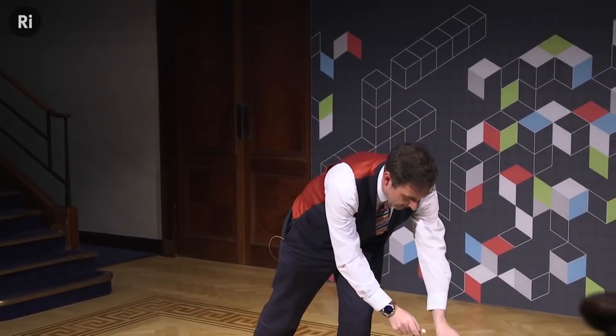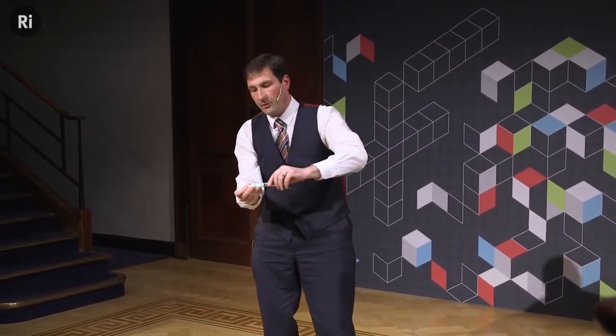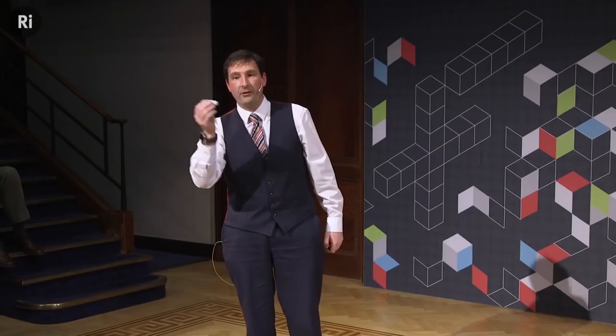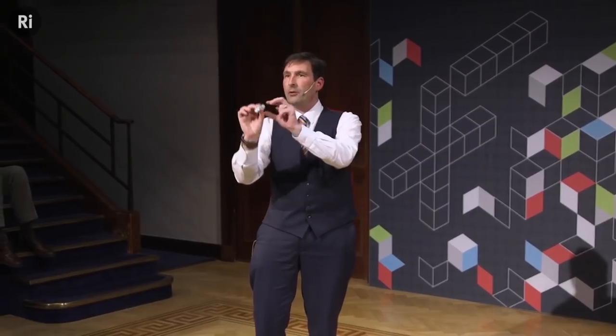But what we've got inside this cell, if I was to open it up, is our roll of materials, all tightly packed. Don't do this at home, by the way. At home, this is full of caustic electrolyte, and it will do you no end of harm. Do it when you make these in the lab for fun, and you don't put the electrolyte in. But what you see in here is a roll, and in that roll, we've got the layers of anode and cathode material separated by this white separator material, polymer separator material. And that simply gets dropped into the cell can. We weld the electrode to the bottom. We weld an electrode to the cap. As Simon so eloquently put it, we squirt in some electrolyte, typically under vacuum, and then we seal the whole thing up, and we take it off and charge it for the very first time.